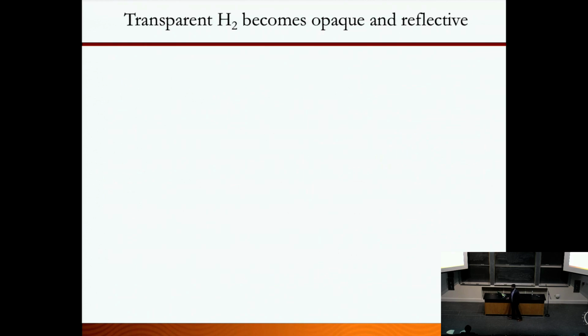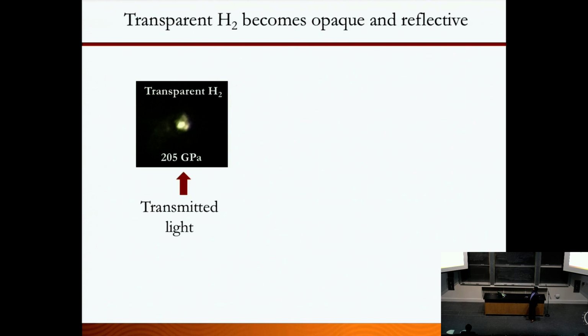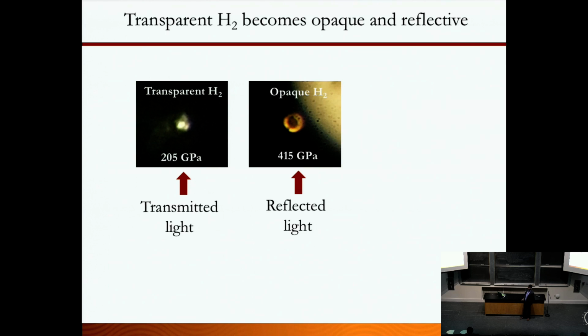So the story starts from here. While we were squeezing this to really higher pressures many times, what we observed is, at lower pressures, this is a picture you're seeing at 200 GPa from the transmitted light. So it's transparent. This white thing you're seeing in the middle is the transmitted light, and it's an insulator. It's a transparent hydrogen. But if you squeeze a little bit further, another 200 GPa, this is only from the reflected light, and you see opaque hydrogen.